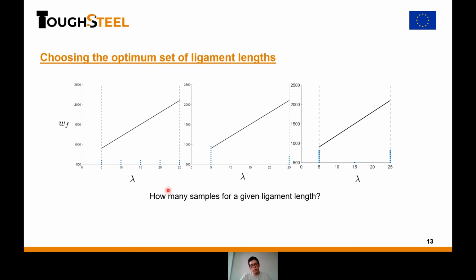But a question that we can ask ourselves is, is there a better way to place those samples? So for instance, maybe it's better to have more samples closer to the lower bound and a bit less samples at the upper bound, or maybe it's something different where you have half at the lower bound and half at the upper bound, but 1 or 2 samples in the middle. And moreover, now that the sample size is dependent on the ligament length, if we have more samples with a small ligament length, this means that we would reduce even more the total amount of material needed.